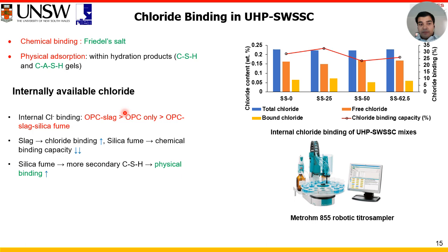We found that internal chloride binding capacity was highest in the OPC slag binary mix, followed by the control mix, and the binding capacity was lowest in the silica fume based ternary mix, which is corroborated by literature, because literature suggests slag can increase the chloride binding capacity. However, inclusion of silica fume can significantly decrease the chloride binding. But as the silica fume can produce more secondary CSH, there is a chance that the physical binding can improve.